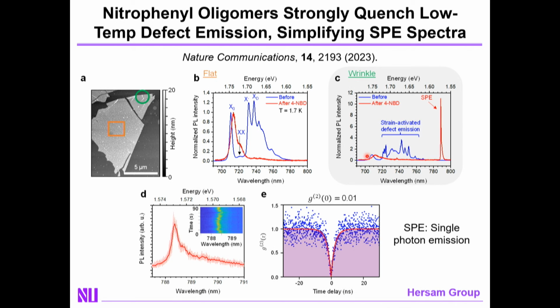The problem, though, is that this defect emission is very complicated. There's many overlapping peaks. The single photon purity is quite low. And as a result, the question is, is there a way to clean up this spectrum? And what you observe is that when you put down the organic add layer, these peaks are largely quenched. And instead, what you see emerging is a single, very sharp single photon emitting peak. This peak, if you then perform so-called G2 measurements, shows very clear indication for single photon emission. So the point here is that the mixed-dimensional heterojunction cleans up the single photon emission spectrum, giving you high single photon purity.